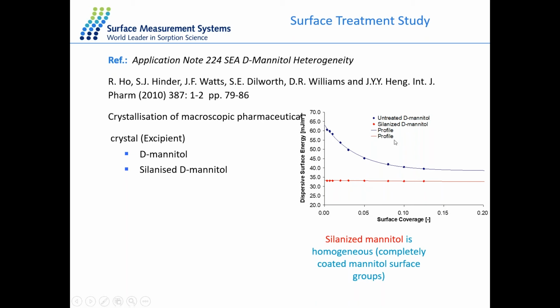There's a few things that we can see here. One of which is that our silanized sample has a much lower surface energy compared to our untreated D-mannitol. What we can also see is the shape of the profile. For silanized mannitol, we have a very linear profile, and for the untreated D-mannitol, we have quite a curved profile, especially in this region here. What this is telling us is that at infinite dilution and very small concentrations, the molecules are small enough to interact with high energy sites in the sample. As a result, we have a high surface energy for untreated D-mannitol. However, when we silanize the material, silanization has caused these areas to be blocked. In this case, we lose this area of surface energy, and that's why we have a more linear plot.